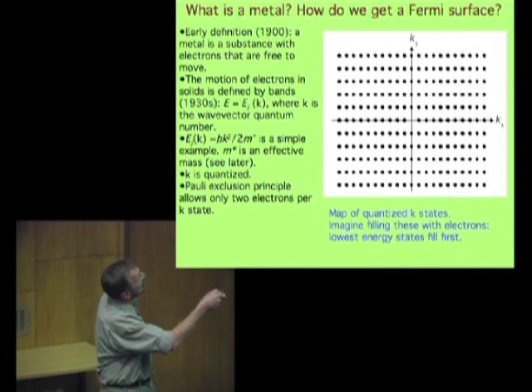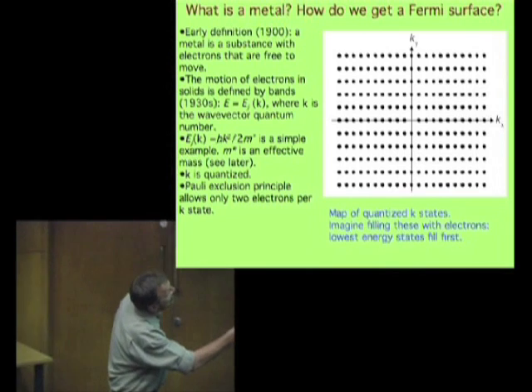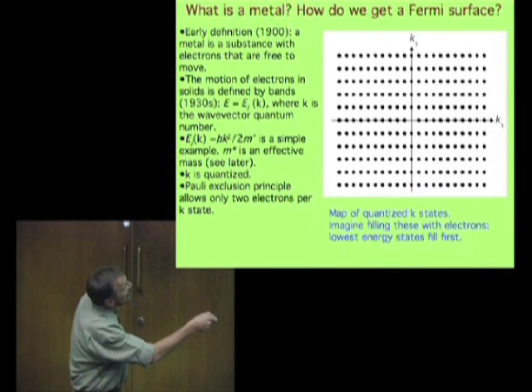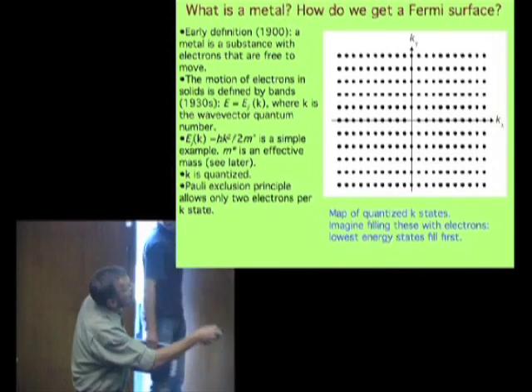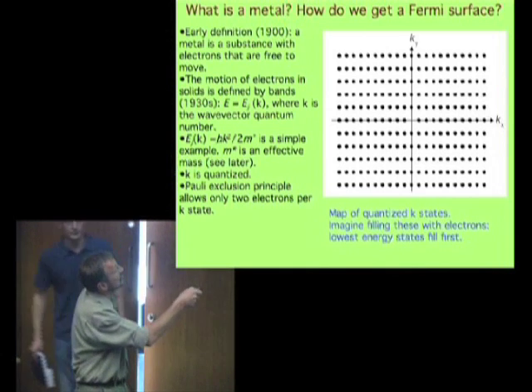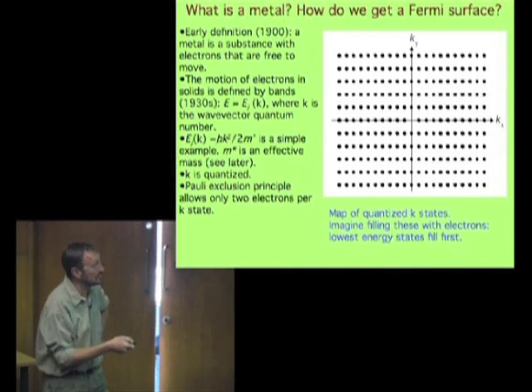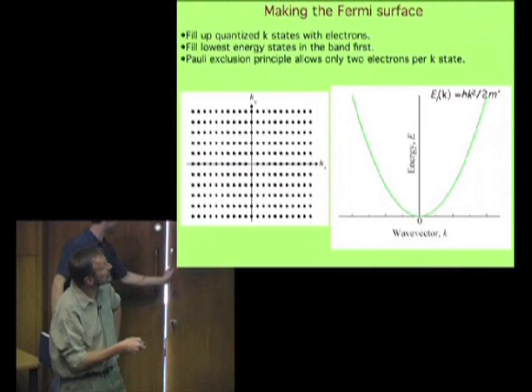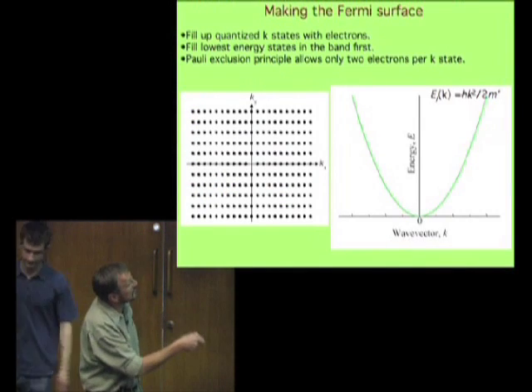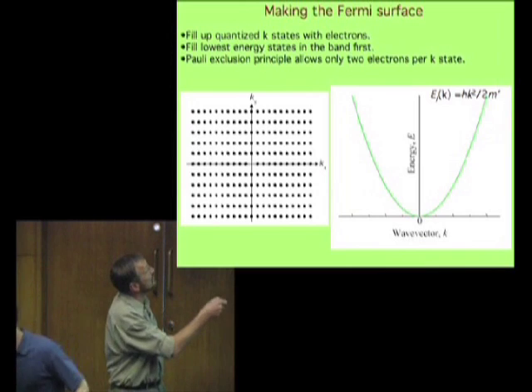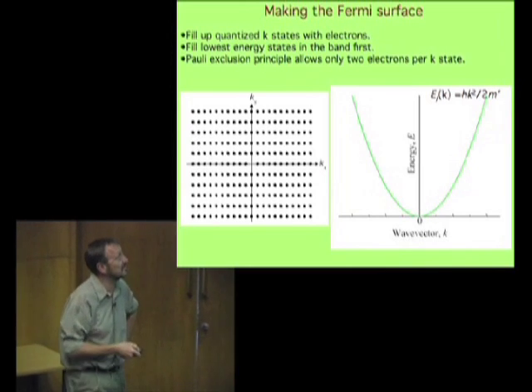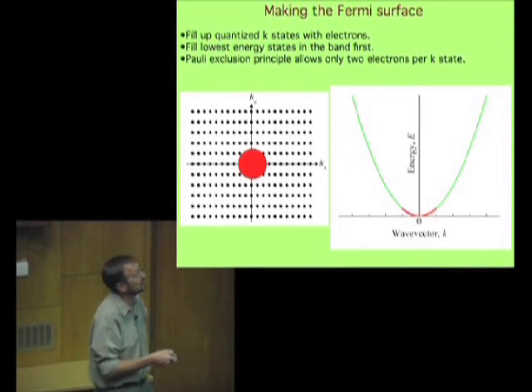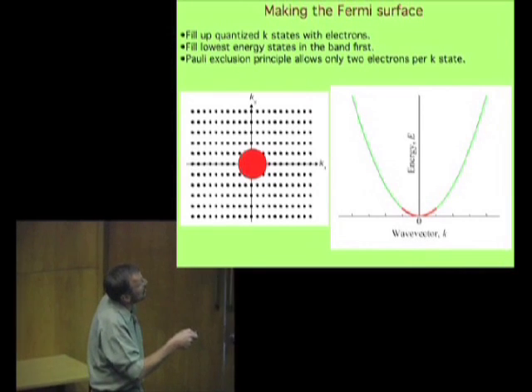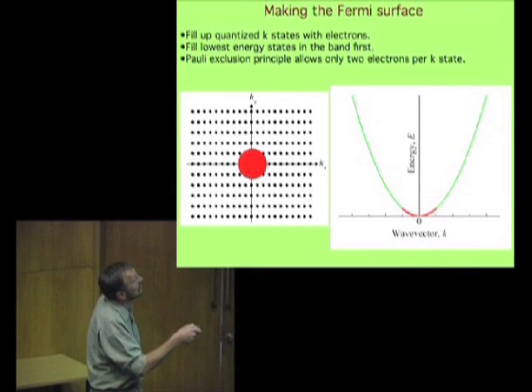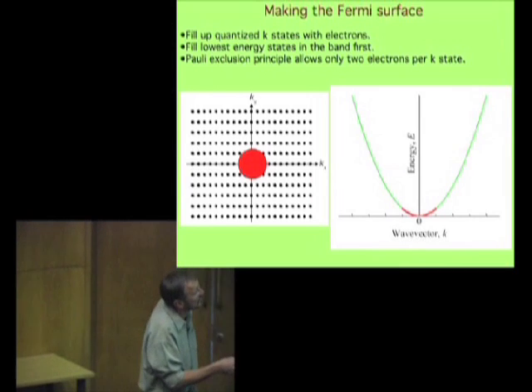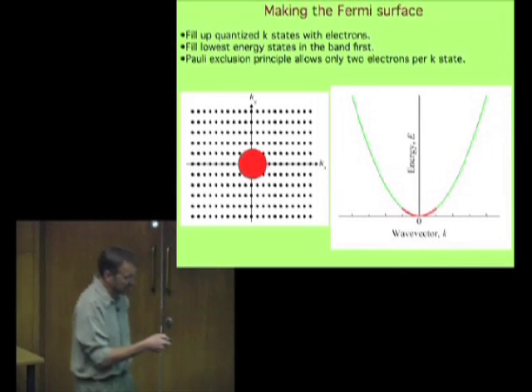If we go with this dispersion relationship, the minimum energy is going to be at the middle here, and then as we work outwards in K, we're going to get larger and larger energies. So let's imagine that we have a solid which is empty for the time being. This is its dispersion relationship. This is a map of the K states. What we're going to do is put in electrons. So we first put in a few electrons. They occupy the states nearest zero wave vector. That gives them the lowest energy. So they fill up this band to this sort of height here.